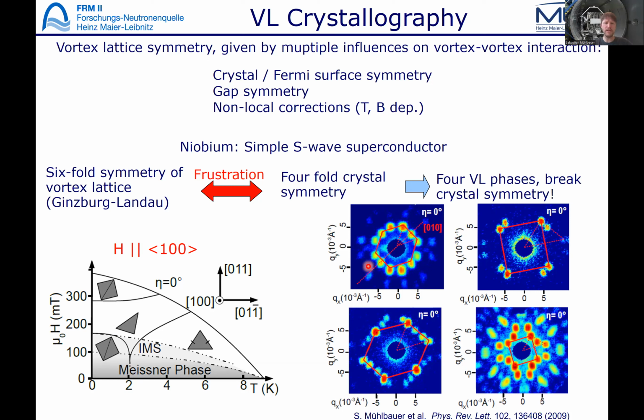And a very simple example I chose here, and I guess everybody knows that, and also Ted, you know that. This is niobium, which is a very simple S-wave superconductor. And in niobium, you get very nice frustration effects when you apply the magnetic field along a 4-fold crystal direction. There are several ways of putting a 6-fold vortex lattice on your 4-fold crystal axis, and you get really very nice different vortex lattice symmetries. So this is really doing a diffraction experiment, a crystallography experiment on this superconducting vortex matter.